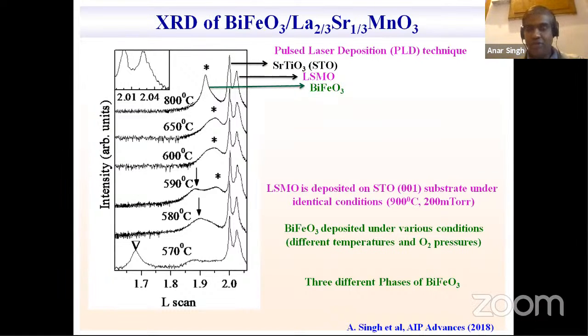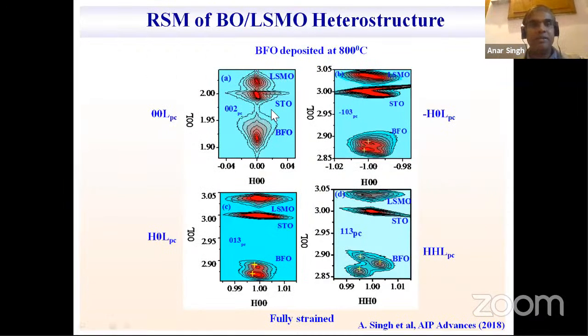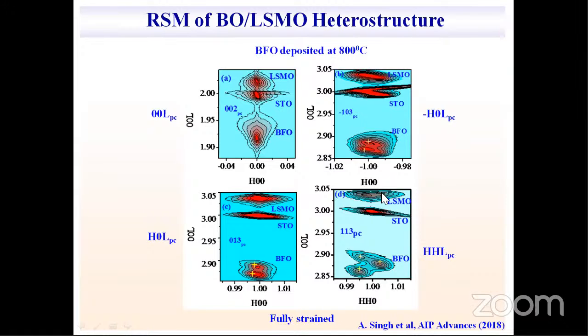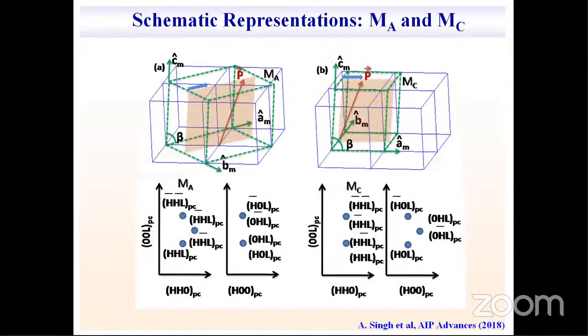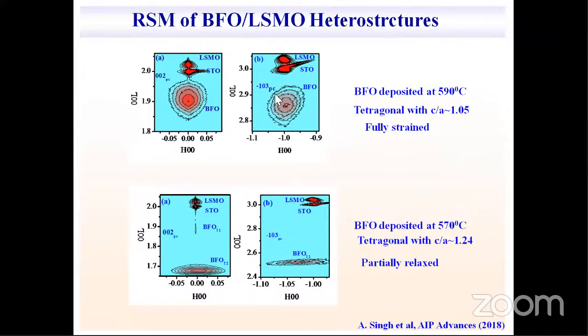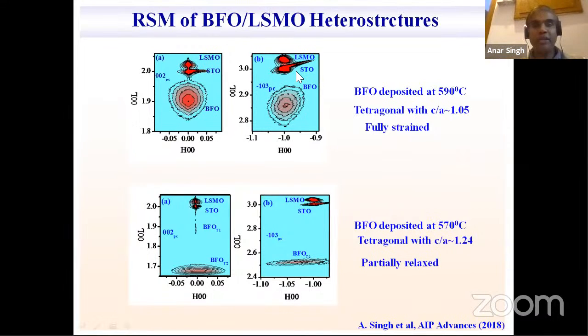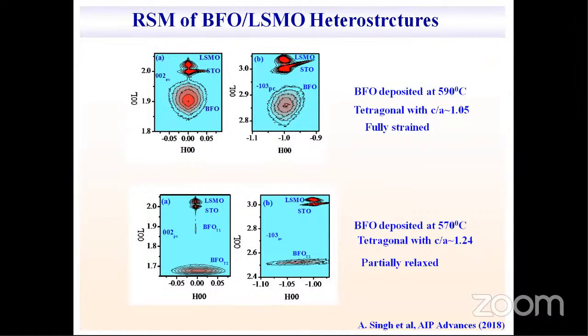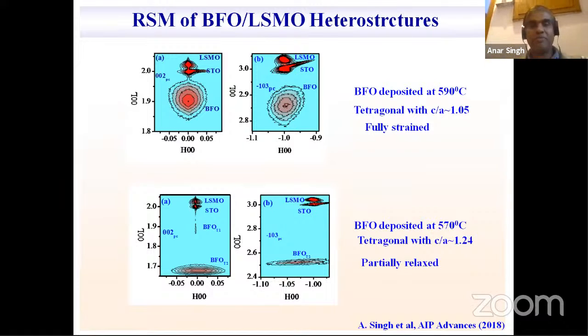Okay, thank you. So I will try to summarize quickly. We have done reciprocal space mapping to analyze the crystal structure of these films using the X-ray diffraction pattern, and from this analysis, we have observed that our bismuth ferrite transformed from a monoclinic structure